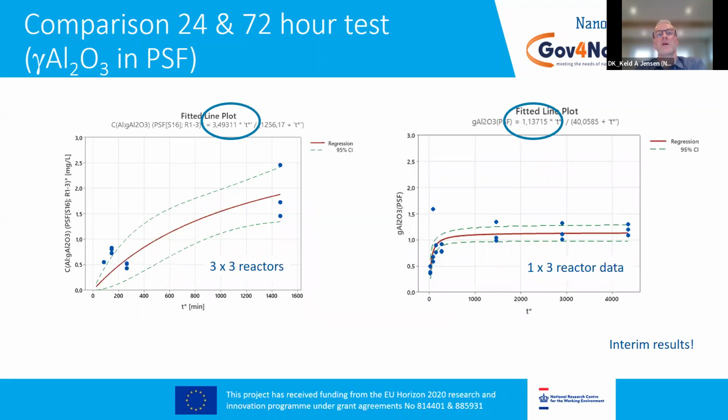When we looked into the phagolysosomal fluids, I mentioned before that this data set was not optimum. We seem to have some scatter, and indeed, when we did our second experiment, we did find a somewhat lower solubility limit for that experiment, and I think it's quite reliable as we see a very constant concentration over the 3 days in the setup. So this should be a reliable data set. So we see that the 3-day experiment improved the 24-hour test, and we are quite certain about the results here.